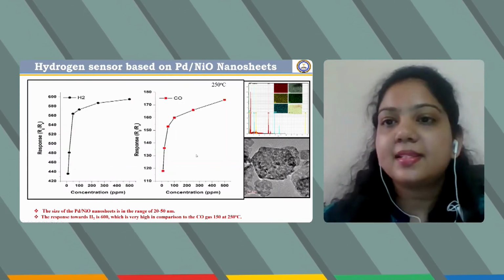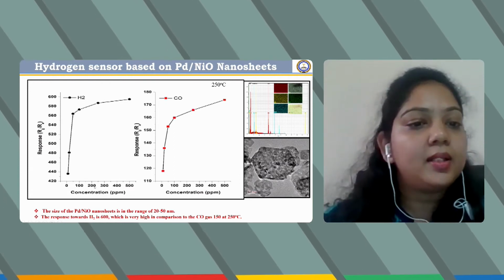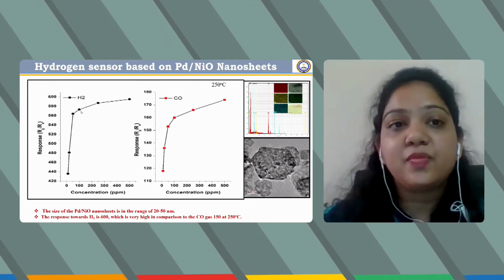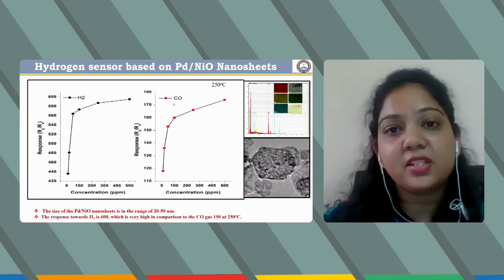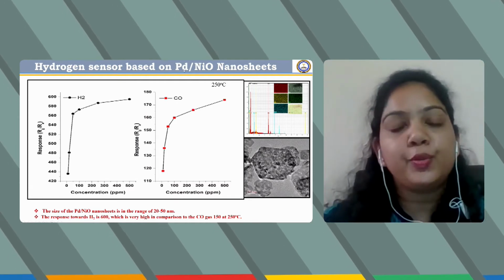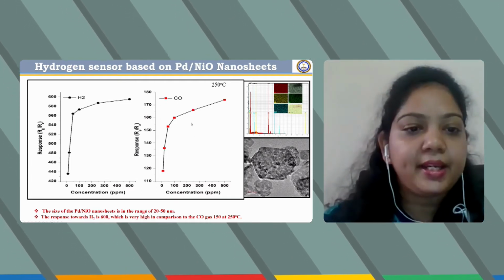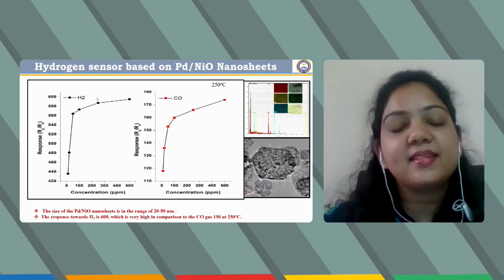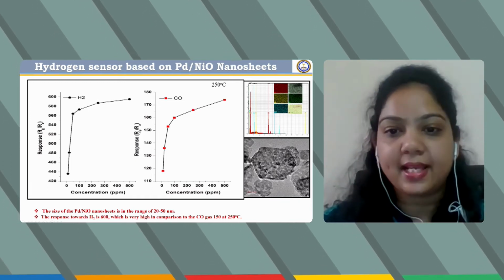So now the results show that the gas sensing response is very high towards hydrogen in comparison to CO, due to the catalytic effect of the palladium. It is very high, almost 600, which is a very good response for a sensor.